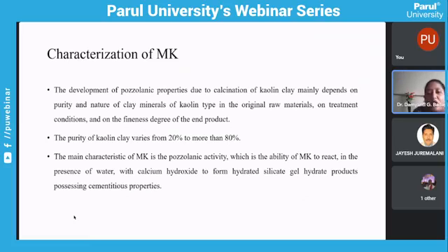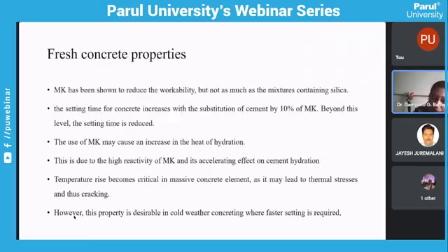And the main characteristic of metakaolin is the pozzolanic activity, which is the ability of metakaolin to react in the presence of water with calcium hydroxide to form hydrated silicate gel, a hydrated product possessing cementitious properties, and that is very important, right? So the high reactivity of metakaolin will affect the cement hydration. Okay, heat of hydration may be increased, and setting time will come into the picture. If temperature rise becomes critical in massive concrete elements, it may lead to thermal stress also. So we have to also control the temperature of concrete. However, this property is desirable in cold weather concreting.